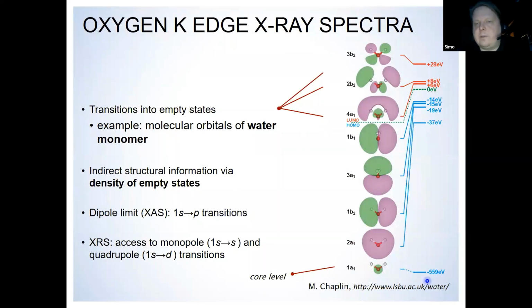And it's 500 electron volts, and this is of course in the soft X-ray range. Typically this is for the molecular orbitals for water, a single water molecule. We have basically the 1s oxygen orbital here, and then you have the HOMO-LUMO gap, and then basically one sees in the spectrum these unoccupied orbitals. So one gets this indirect structural information through the density of empty states when one looks here.